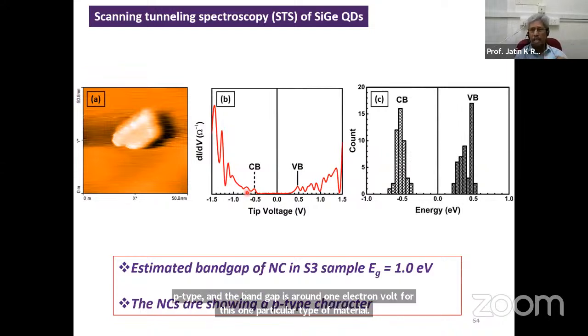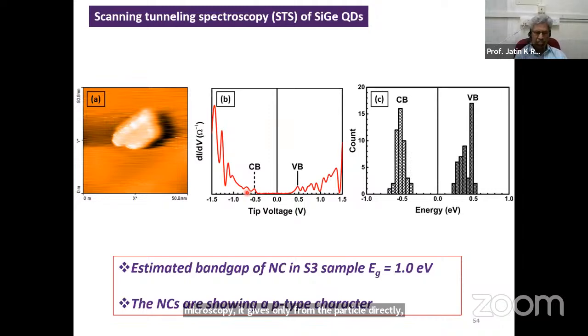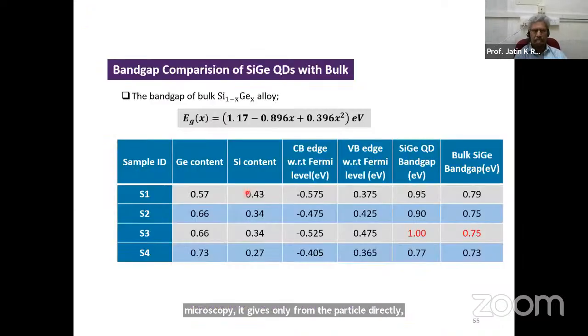So why is it n-type when you do conducting AFM, and p-type when it comes to scanning tunneling microscopy? The two methods give different values. We think that in conducting AFM, it's touching on the top of the oxide layer. It's giving n-type nature, and the band gap is also high. Whereas scanning tunneling microscopy gives results only from the particle directly. So that gives you a lower band gap and also a slightly p-type character.